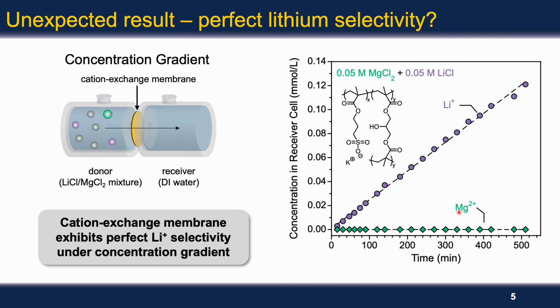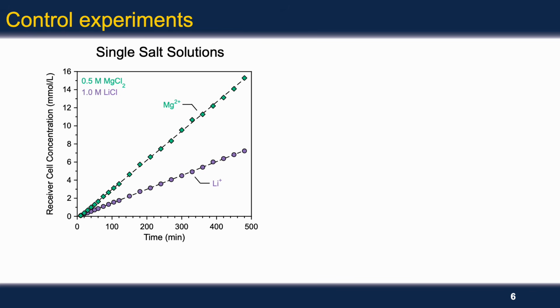This suggests essentially an infinite lithium to magnesium selectivity, and this is not something that we expected from a negatively charged membrane, which is expected to permeate magnesium ions faster than lithium ions. And this is indeed the case if you do single salt diffusion experiments across the same membrane. We did some control experiments where we had single magnesium chloride or lithium chloride transport across the membrane, and in this case we do find that magnesium chloride permeates faster than lithium chloride.